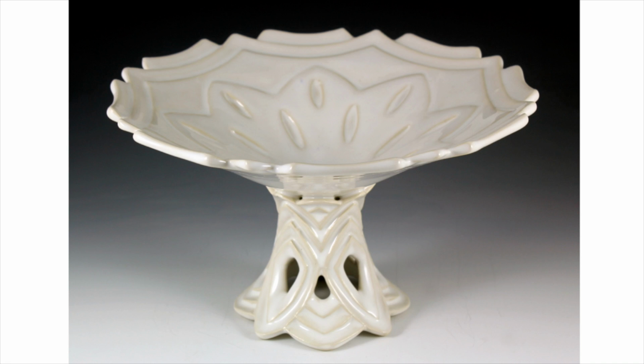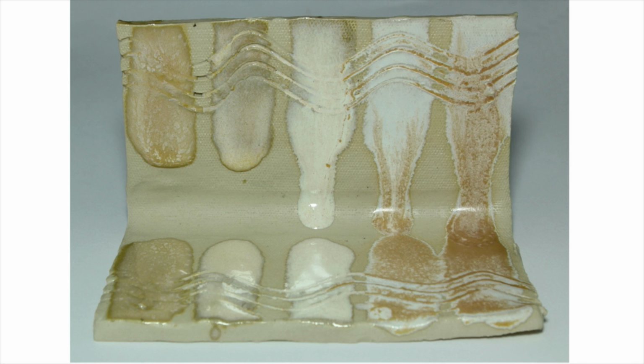Or you can take out the dominant flux in a glaze recipe and then add it back in 5 to 10% increments. Note how runny the glaze gets as more of the dominant flux is added.